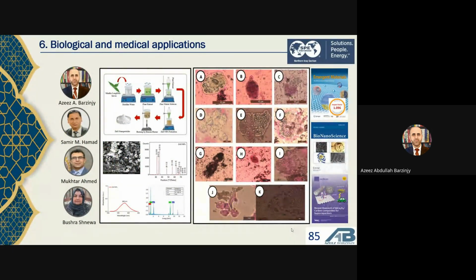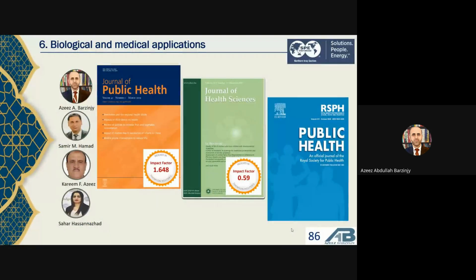Regarding biological projects, we started with some medical application. For example, we utilized zinc oxide nanoparticle in order to kill some unwanted bacteria. Here in this case, we have lamb liver, and we leave the lamb liver in a bare environment in order to grow bacteria, and then we utilize zinc oxide nanoparticle. After a short time, we realized that this nanoparticle can kill this bacteria more effectively than the normal additive or normal catalyst that we used before.